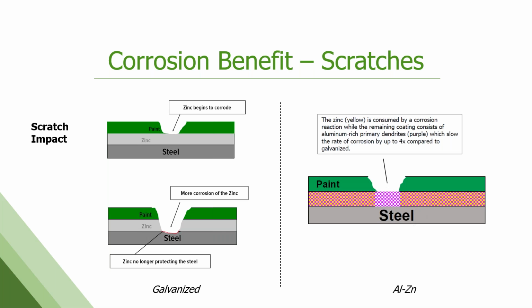Whereas on the right with the aluminum zinc product, so imagine you have the lattice, right, of our yellow, which is the zinc, and the purple, which is the aluminum. So the zinc sacrifices itself and goes away, but you still have this aluminum structure, crystalline structure there that prevents you getting down to the base steel and that red rust, and still gives something for the paint to adhere to. So you're less likely to get paint peeling back from scratches because it still is adhered to the aluminum. And again, it's about, on average, the rate of corrosion is about 4 times slower than galvanized.